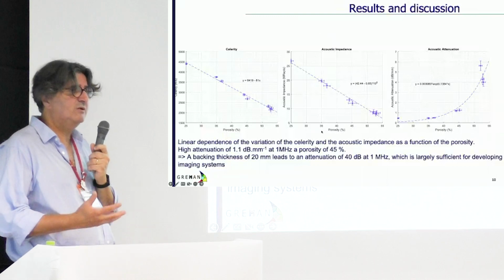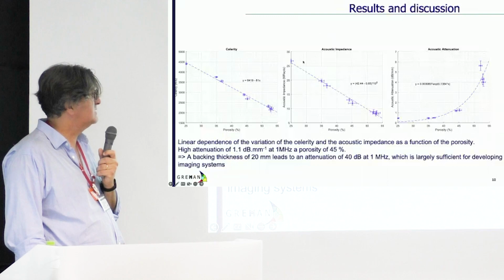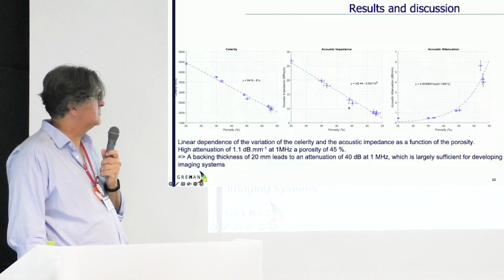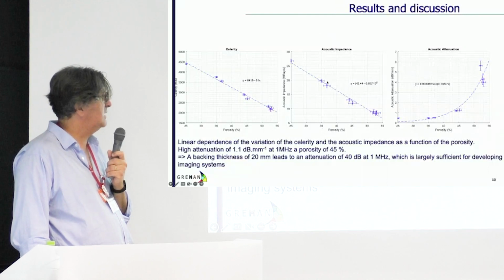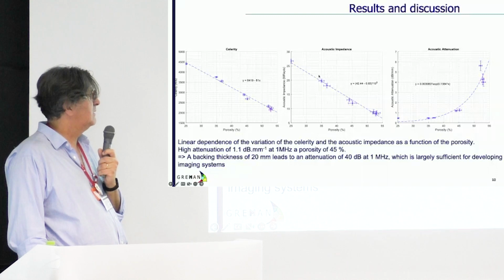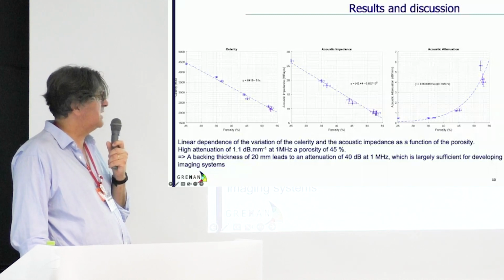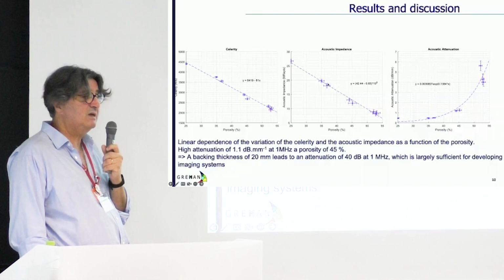Of course, because you increase the air porosity, you decrease the acoustic impedance. And surprisingly, in this range, the acoustic impedance still remains linear. So you can control the acoustic impedance, which is very interesting.